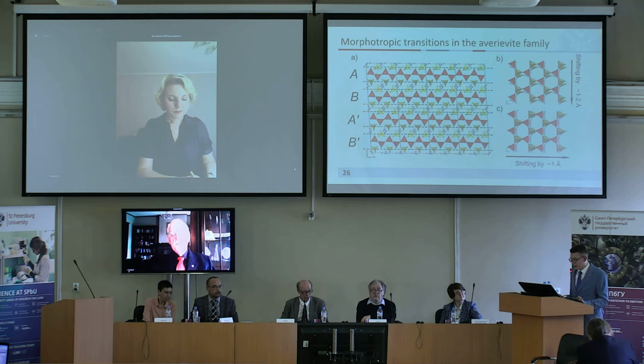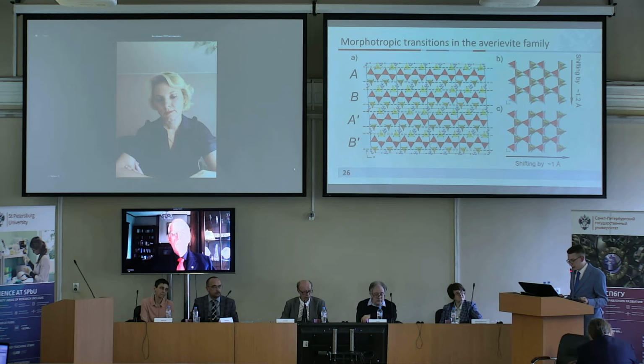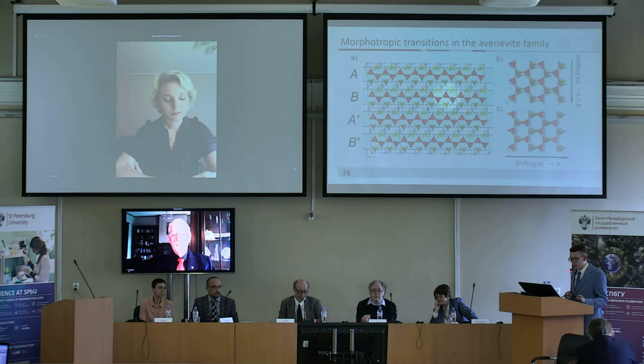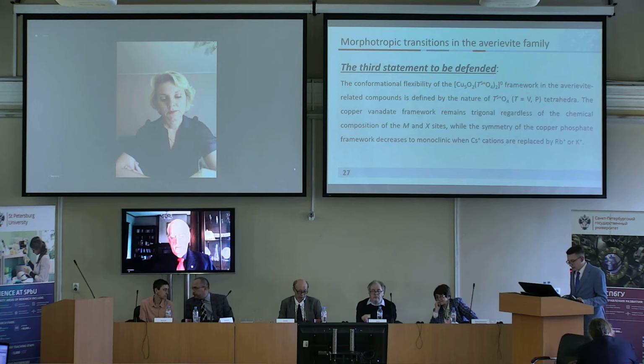The distortion of the copper polyhedrons leads to a decrease in the symmetry of the framework, the displacement of the layers of oxo-centered tetrahedrons. Thus, in the cesium phase, the framework remains trigonal, while when cesium is displaced by rubidium, the symmetry decreases to monoclinic. The data described above lead us to the third proposition. The type of tetrahedral complex determines the conformational flexibility of the framework.